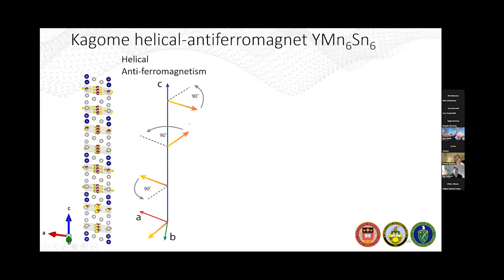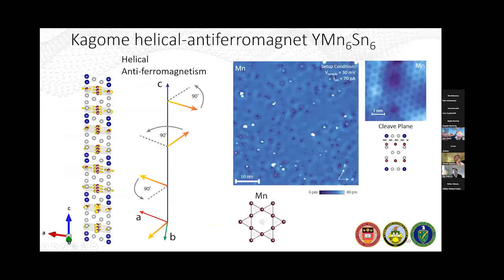So yttrium manganese tin is again this helical antiferromagnet. And once we successfully cleave it and are able to locate a large flat region of the sample, this is what a topograph looks like. This is a topograph of the manganese layer. If you zoom in, you can see this hexagonal lattice of the manganese atoms. And then this is the large scale topograph. It has this hexagonal lattice that underlies behind, you can kind of see there, and also several different impurities that will actually serve as good scattering centers for our QPI measurements.